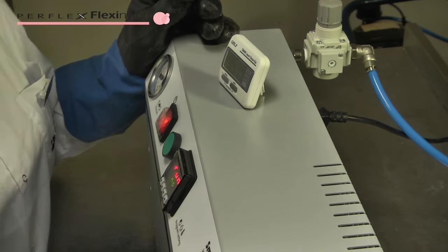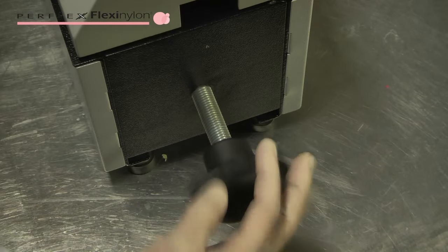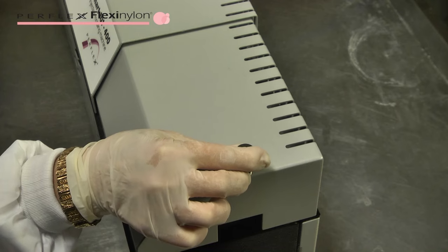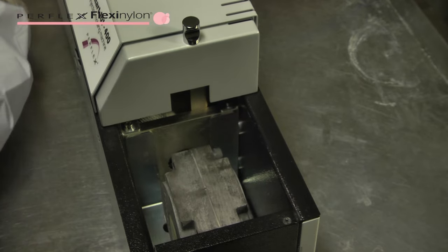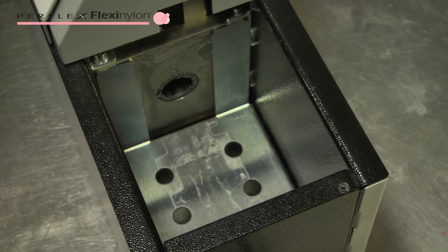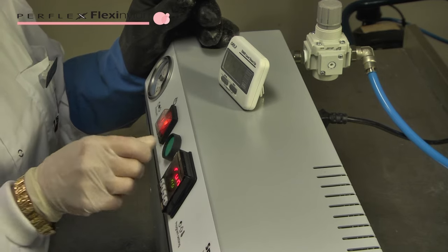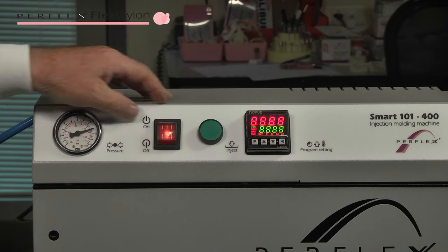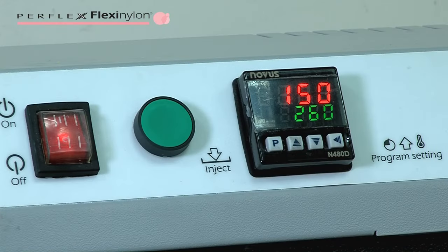Set the external timer for 5 minutes. Leave the flask inside the injector to cool under pressure when the furnace is switched off for 5 minutes. Release the flask from the injector by pressing the button again. Open the black handle of the Smart 101-400 till the end stop. Always keep the door closed. Press the button again to release the flask and remaining cartridge. Take the flask out using heat protection gloves and bench cool for approximately 30 minutes. The flask should still be a little warm for the opening process. Close the door. Press the button again to insert the piston back and switch off the machine by pressing the red button. The machine temperature should reach 150 degrees Celsius before activating again for a new injection.